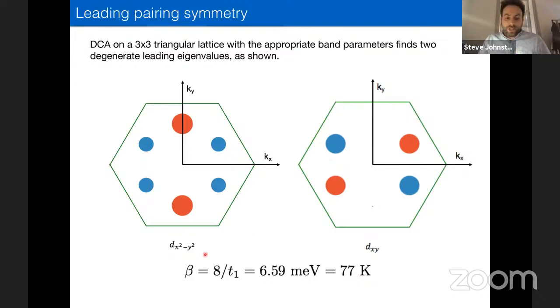So because these are degenerate, what we actually expect to have happen is the solution is going to be a linear combination of the two. So it's a d+id pairing instability, or at least that's what DCA is predicting is the dominant pairing instability in the system. And in this case, it's actually winning by quite a large margin at this temperature.